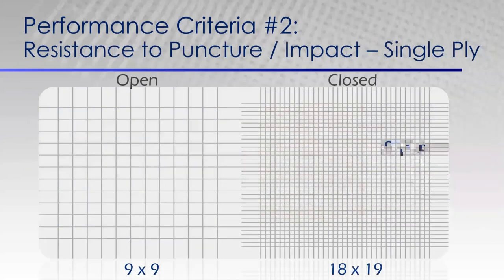So we look at our single plies, we look at that fabric package. And as I mentioned, most of your single plies, your EPDMs, your TPOs, and many of your PVCs have that open 9x9 stitch per inch open fabric that provides that reinforcement for the coatings of these systems. What you'll see in contrast is an 18x19 closed stitch, which is a denser product, which gives you greater puncture resistance on the roof. So open weave, not as much puncture resistant; closed is more dense.